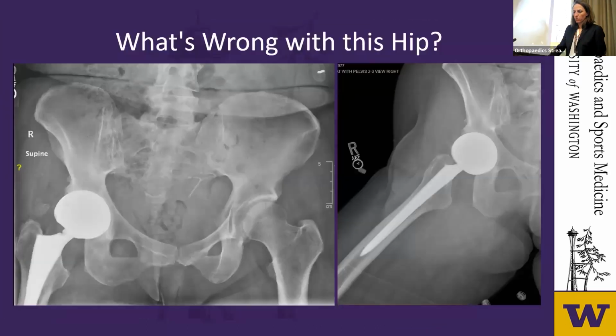So, there are a few things that are kind of scary here. One is that cup's clearly not in 40 degrees of abduction. It's maybe 20 with a tailwind. And it does look excessively anteverted to me, although without a CT scan, I can't say that for sure. The thing that really gives us a pretty good sense of what's going on here is the notching on the femoral stem, and that notching is happening because she is coming up in external rotation up against the backside of the cup, which is the most likely etiology here.